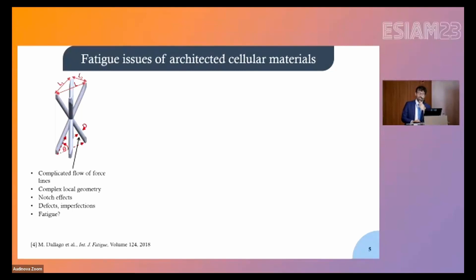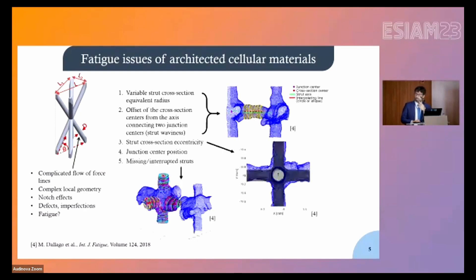The fatigue behavior of these materials is still poorly understood, even though it is of great concern for industrial applications. This is mainly because the architecture of these materials is an intrinsic weakening factor, due to the complex force flow lines producing elevated stress concentration at the nodes. In addition, there is a synergistic effect with manufacturing imperfections, which introduce additional stress risers into the lattice.